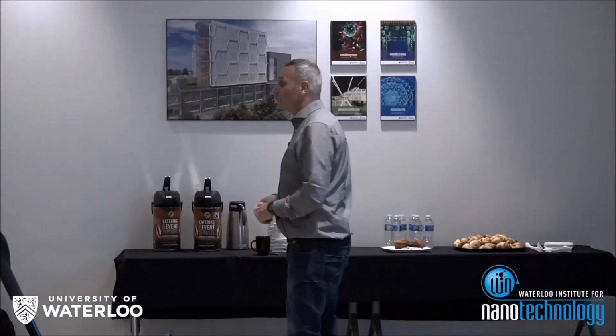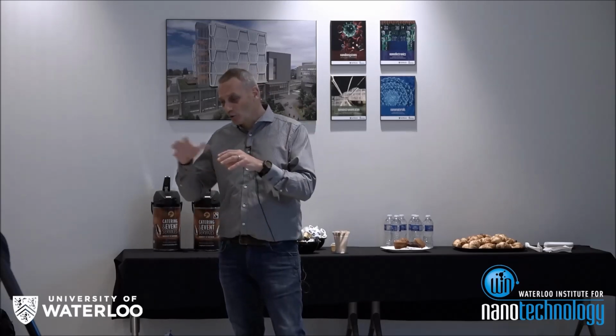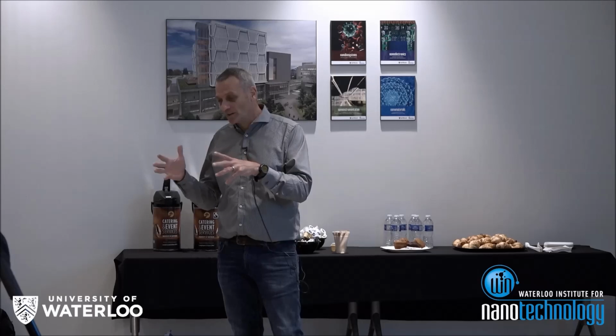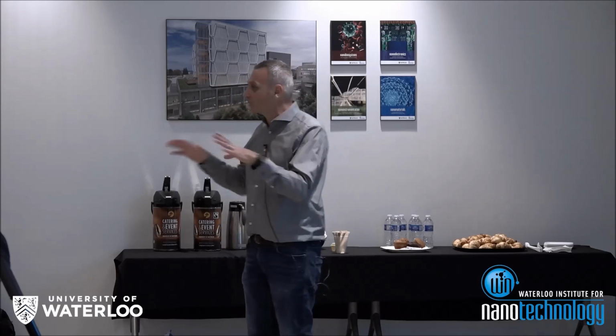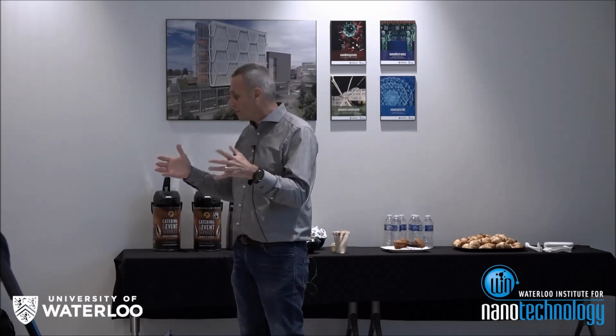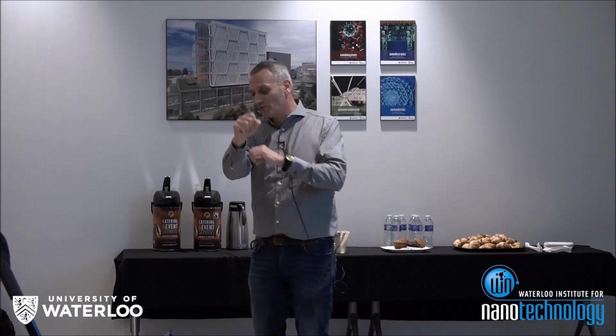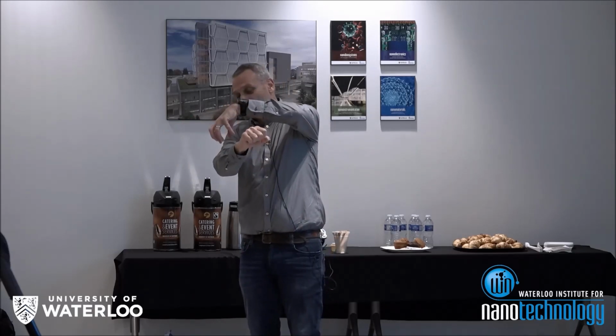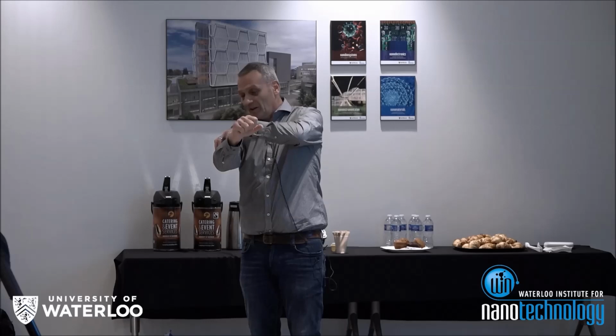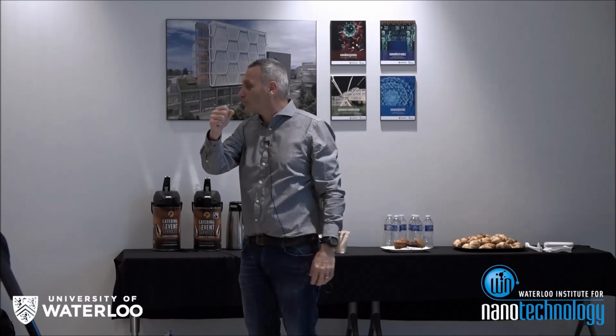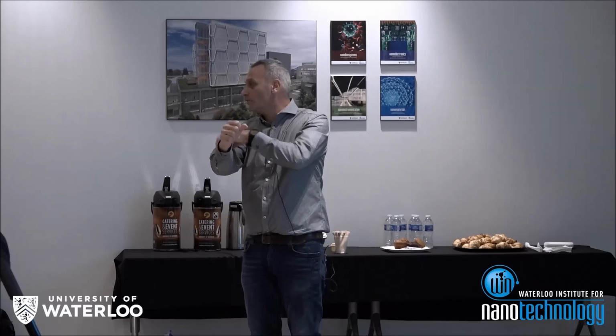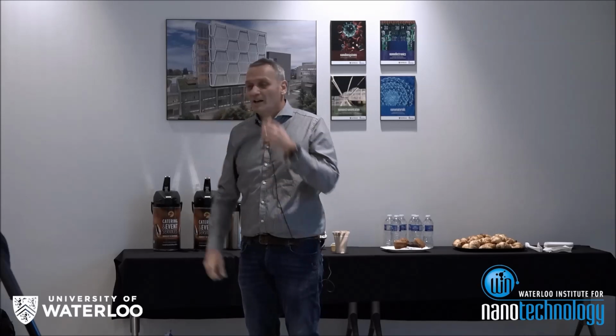Yeah, good question. We don't have a lot of experience on that. We wanted to coat some silver nanowires with oxide, and we tried to use electrochemistry, for example. It's well known that zinc oxide or aluminum-doped zinc oxide, you can deposit with electrochemistry. So we wanted to do that. But it was not nice, because with silver nanowires we have some clusters here and here, and it didn't help for the stability, and you can diffuse a lot, and you can absorb a lot, so it was not interesting.